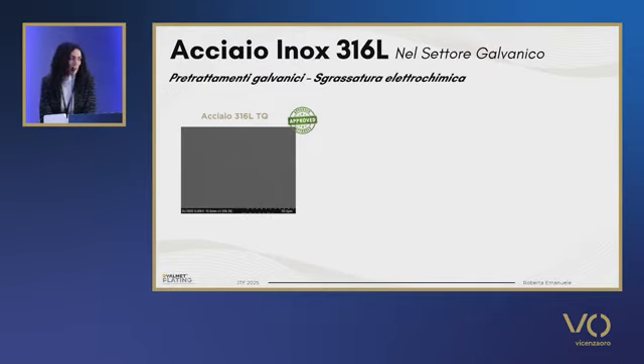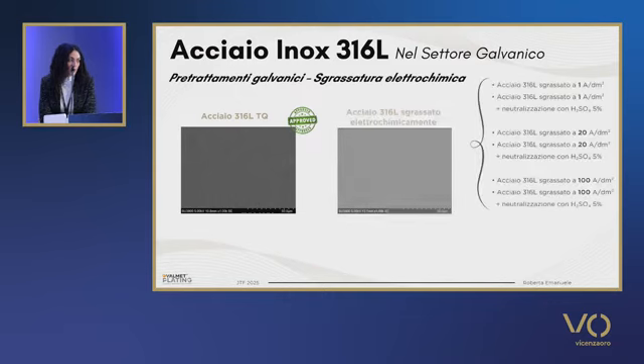This is a SEM test, after the images that were taken after the test. We know that stainless steel 316L does not release nickel unless retreated. We look at the electrochemical cleaning, a process which is always resorted to for adequate coating. Usually it is performed for 60 seconds.